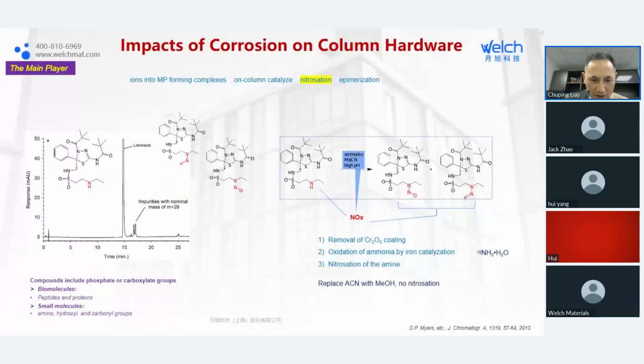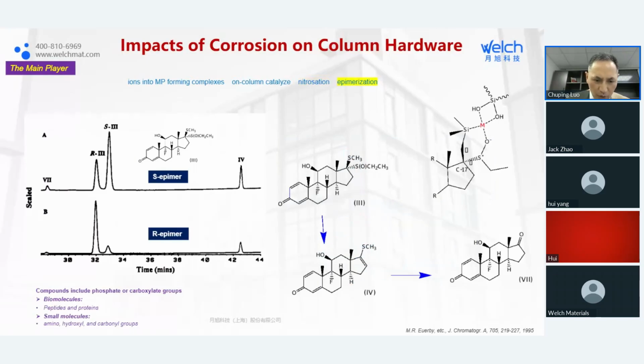epimerization. So you see just one compound injected onto the surface, and on the left side, the top one is the S epimer, but it gives you 4 peaks. But then people say, oh, can I understand that? So they try again, use the R isomer, that's the bottom one, but still 4 peaks. The difference is the ratio between R and S are different. So what's going on here? Eventually they figured out, this is because of this compound, you see that sulfur group, it can be inhibited by a certain path, give you compound 4. And then further give you compound 7.